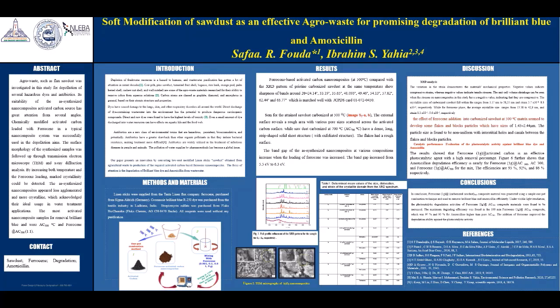The title of my research is Soft Modification of Sawdust as an Effective Agro-Waste for Promising Degradation of Brilliant Blue Dye and Amoxicillin. Abstract: agro-waste such as flakes sawdust was investigated in this study for the depollution of hazardous dyes and antibiotics. Its sustainability for the synthesis nanocomposite activated carbon source has a great attention for several angles. Chemically modified activated carbon loaded with ferrocene and a typically nanocomposite system was successfully used in the depollution aims. The surface morphology of the synthesized sample was followed through scanning electron microscope and XRD diffraction.